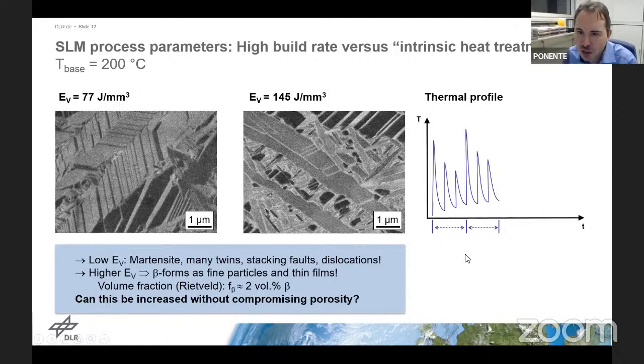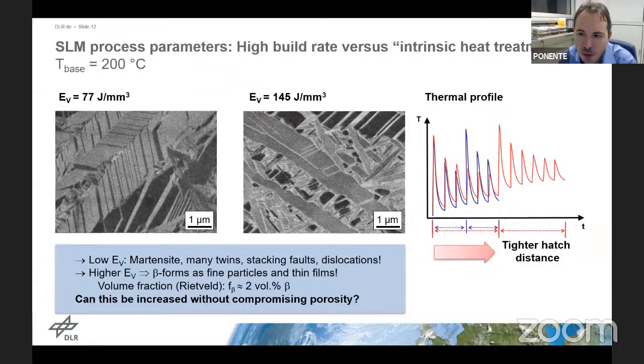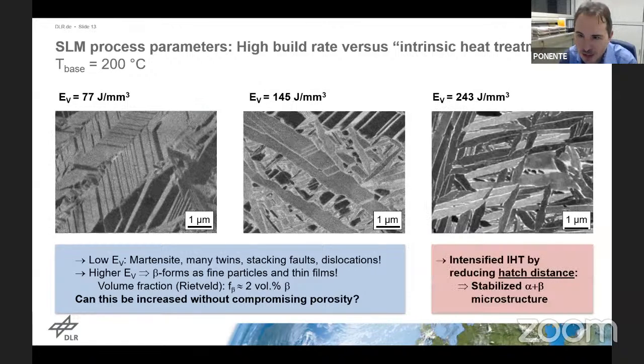Now, if we reduce the hatch distance, so we basically scan the same surface area of the cube much slower, much tighter in terms of pattern, and then we need basically double the amount of time per specimen, then we get an increase in the base temperature, meaning we put more energy into the same specimen, and this indeed did stabilize the microstructure further. That's an effect that we call intrinsic heat treatment because it's unavoidable with the laser processing itself. It's the laser energy itself, due to the changed scan pattern, that increases. So that's where we formed this term intrinsic heat treatment.